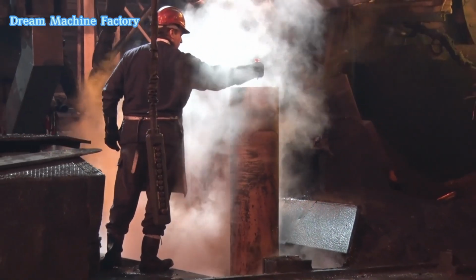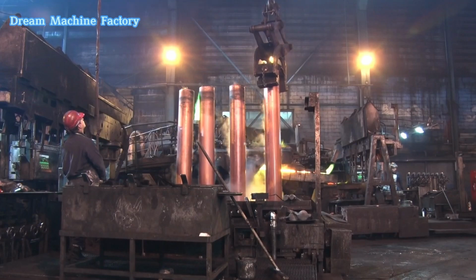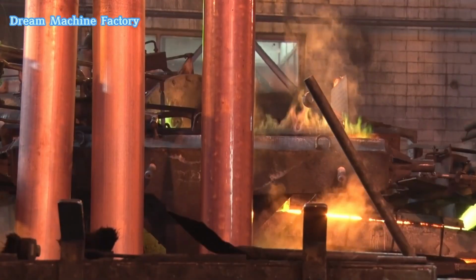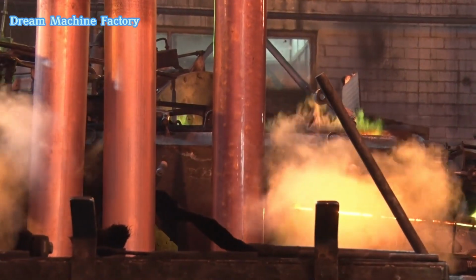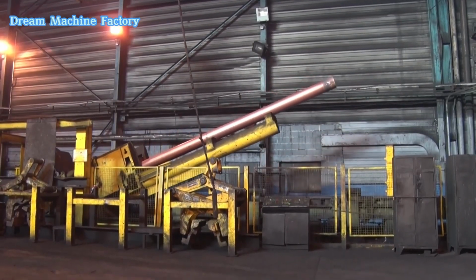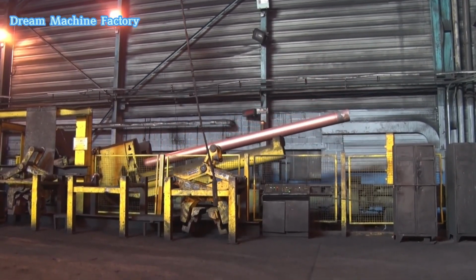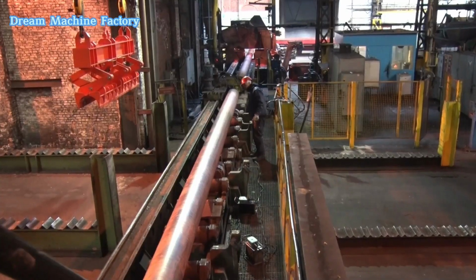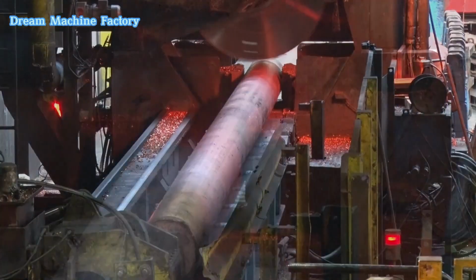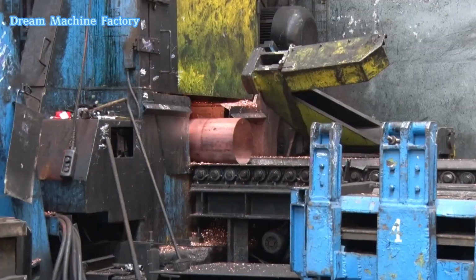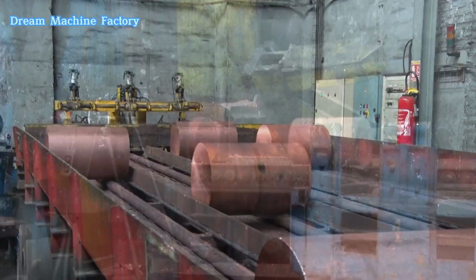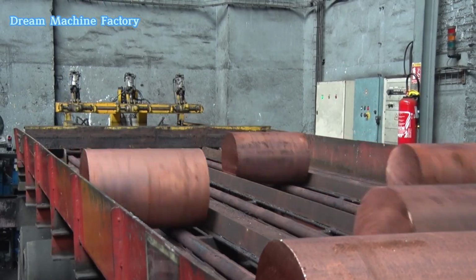Extrusion and tube formation. The billets are reheated to around 850 degrees Celsius and placed into a hydraulic extrusion press. This machine transforms the solid billet into a hollow form by forcing it through a die, while a needle inside shapes the internal cavity. The extrusion process uses pressure of up to 3,150 tons, producing a tube roughly 15 meters